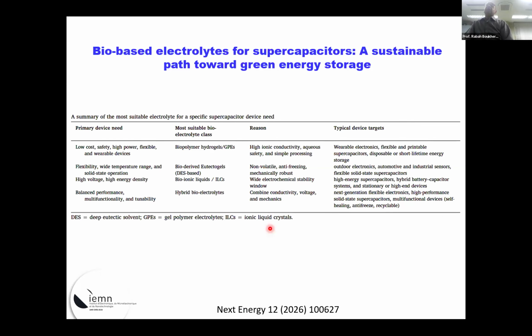It's to develop green electrolytes or bio-based electrolytes. And in this respect, a lot of work, at least academic work, is going on using essentially polymer hydrogels or biopolymer hydrogels, like chitosan and alginate. There are a lot of bio-based polymers. They have a high ionic conductivity.